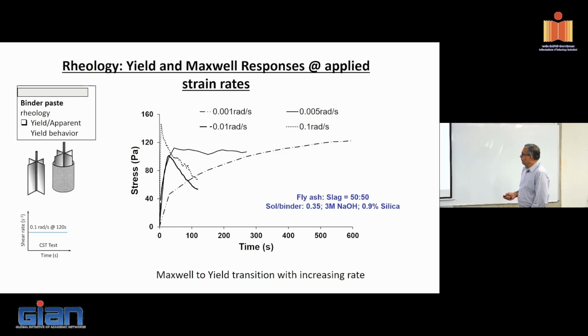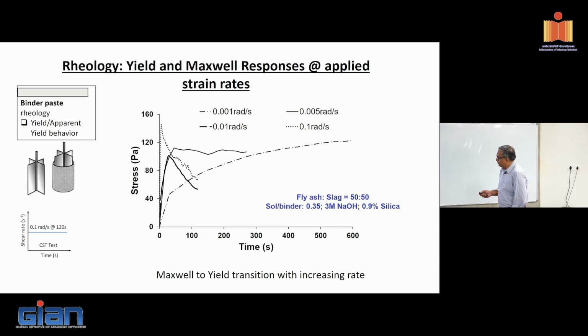So here what we're doing is taking fly ash and slag 50 to 50. Solution to binder is 0.35, 3 molar sodium hydroxide and 0.9% silica content. This is the composition of the activating solution. This is the mass proportion of solution and binder. So basically this is equivalent to a water to cement ratio of 0.335. Sorry, my binder is made up of fly ash and slag in 50-50 mass proportions.